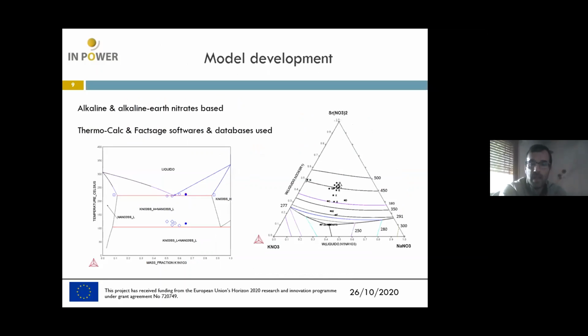As I said, we developed this model for a 4-component system based on alkaline and alkaline earth nitrates. Mainly, we started our work with solar salt, and we started adding other components and seeing if we can enhance the melting temperature and also other parameters. We used Thermo-Calc and FactSage software and databases, and we successfully developed, as I said, the whole system, and we could assess all the phase diagrams that are part of the system.